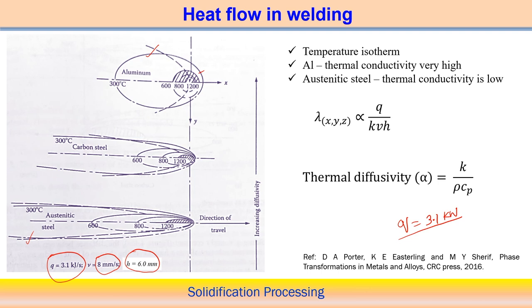And even if the thermal conductivity is very high, ideally if thermal conductivity tends to infinity, then this profile tends to the circular profile as compared to the other cases. So here for the carbon steel, the temperature isotherm shape is in between the aluminium and austenitic steel, because carbon steel thermal conductivity is more than austenitic stainless steel, but less than that of aluminium. That's why we get this kind of profile.